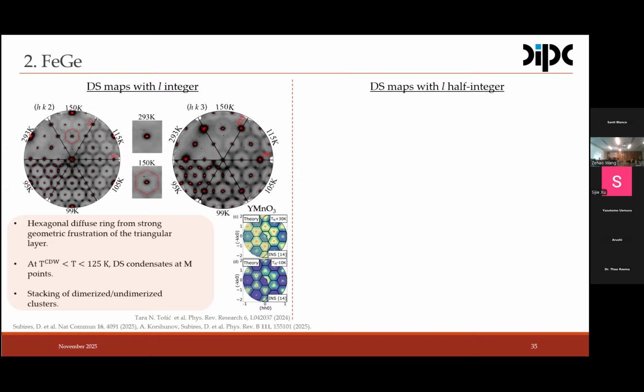At high temperature, we see a hexagonal diffuse scattering, and once we start to cool down, the diffuse scattering starts to condense at the M points, right? And below the transition temperature, which we have here, the charge order transition. The same if we plot at L3: we have the diffuse hexagonal ring, and below 125, 120 Kelvin, the diffuse scattering condenses into a long-range charge order.